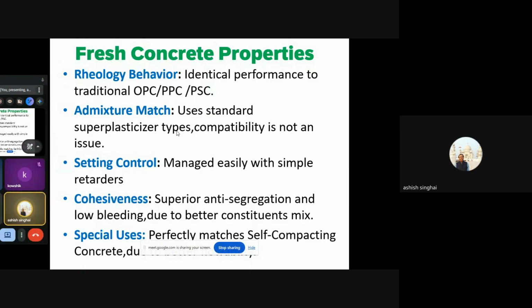As I said, the three different materials are interground in such a manner that particle size distribution ensures that the finally produced fresh concrete will have the least amount of segregation and almost zero bleeding. So that ensures that our concrete has better packing, higher density, and hence better strengths and durability. And what are the special uses? Perfectly matches for self-compacting concrete. You know why it is suitable for self-compacting concrete? Because of the finer ingredients, because of the finer particle size distribution. So the concrete so produced with the use of some very good quality admixtures, possibly PC based, will flow by itself and will be like a self-compacting concrete.